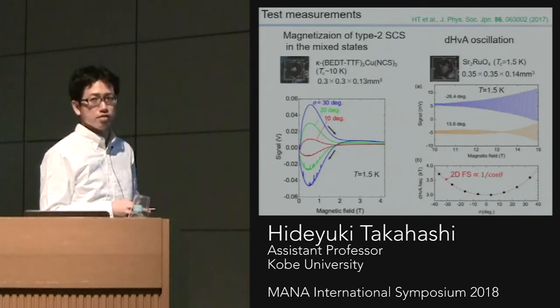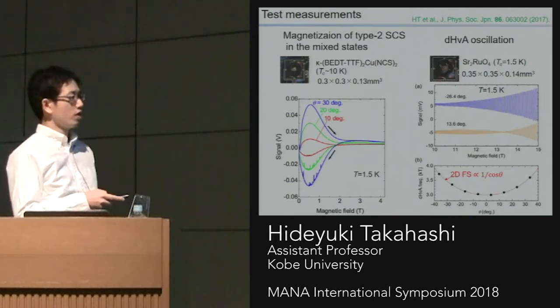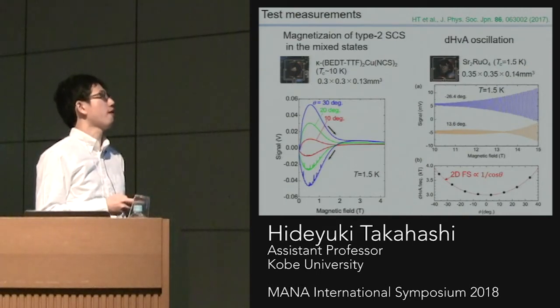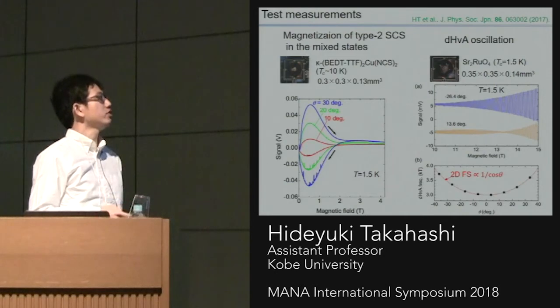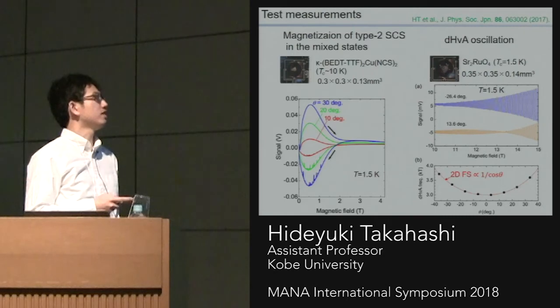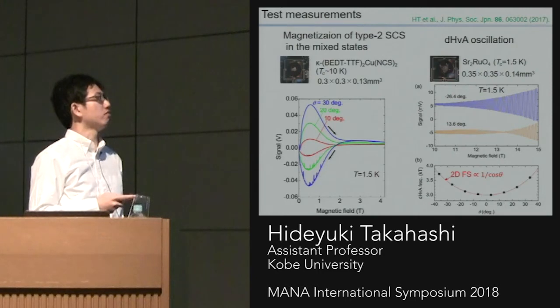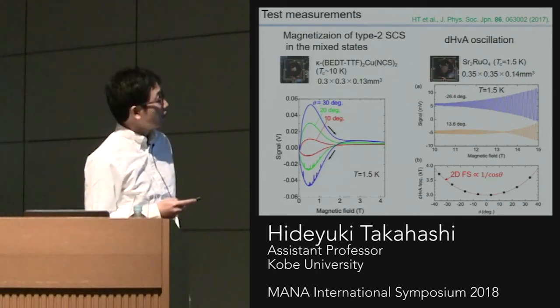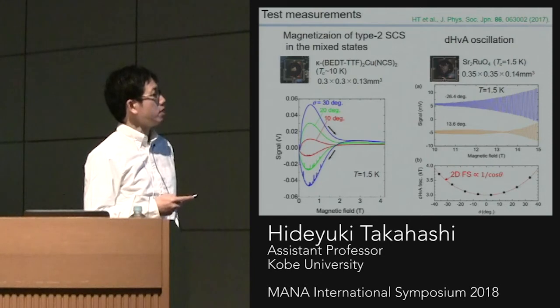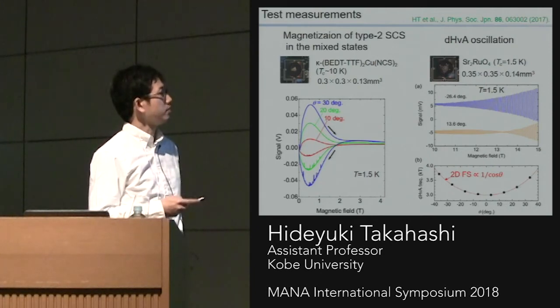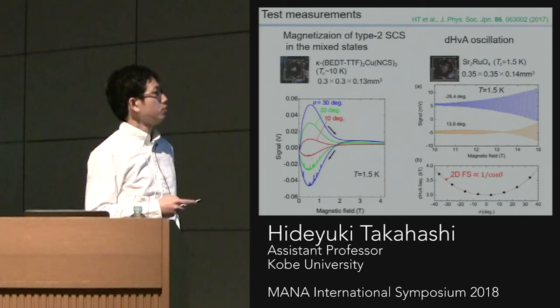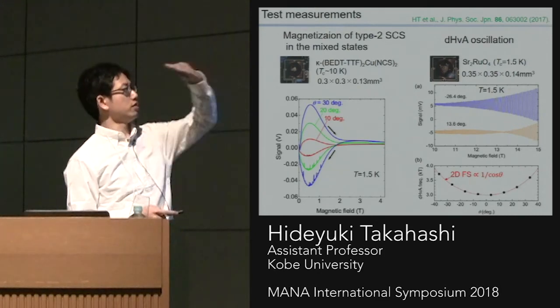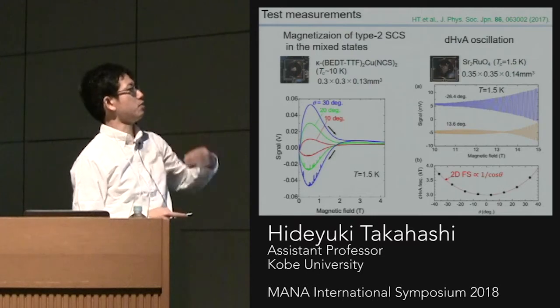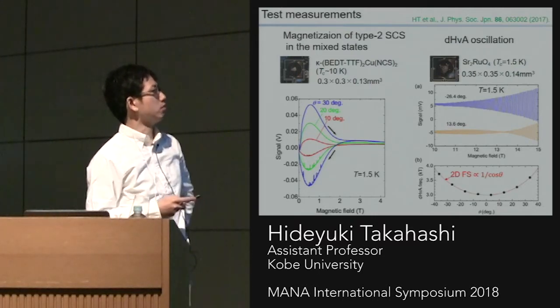Let me show some examples. We measured 2 superconducting samples as test samples. The left figure shows the data for layered organic superconductors whose transition temperature is about 10 Kelvin. The sample has a platelet shape, and the sample dimension is here. The sample C-axis is in the same direction as the normal of the membrane surface.